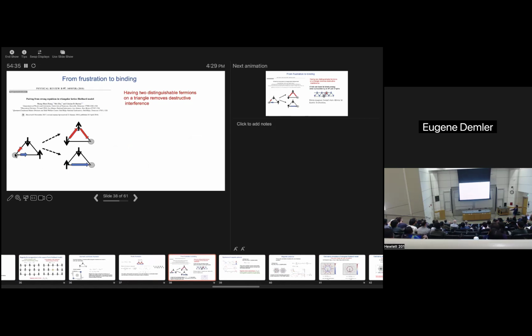He said, let us consider a hole in the presence of spins which are now pointing in the opposite direction. Because now if we do the same exercise, looking at a hole which moves this way, or a hole moves on the upper trajectory, what's left behind are distinct configurations of the spin. And therefore, we don't have to add them, and they no longer add up with opposite signs. There is no destructive interference. So it's energetically favorable to have a hole surrounded by opposite spins rather than the same spin. So there is a bound state.